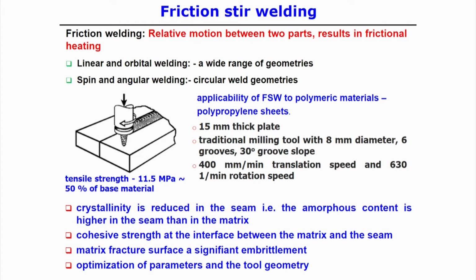So, using this friction stir welding process, although it is a promising technology for joining even non-metallic, plastic materials, it was not very successful because only 50% of the base material strength was achieved by this welding technique. If we look into the typical characterization of the weld joint, we can see the crystallinity is reduced in the seam. Definitely there is a stirring of the material in the seam, that means the amorphous content is higher in the seam than in the matrix material.